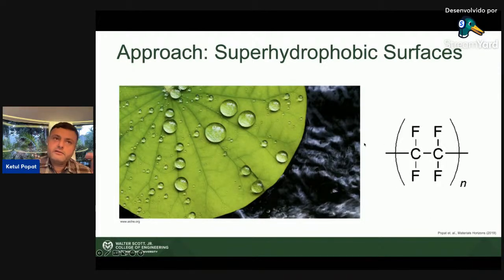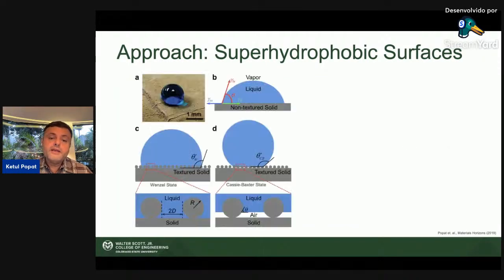So we thought that we can create textures. We know that. To create chemistries, maybe we can use a carbon-fluorine bond because we know Teflon is very hydrophobic. So if you combine the CF bond with the textures that we create, can we create superhydrophobicity or not? And so what we found out, and I won't go into the detail of the theory of superhydrophobicity, that has to do a lot with the Cassie-Baxter state, where you actually trap the air in the texture of the surface because you have a chemistry and the drop of liquid remains a drop of liquid.